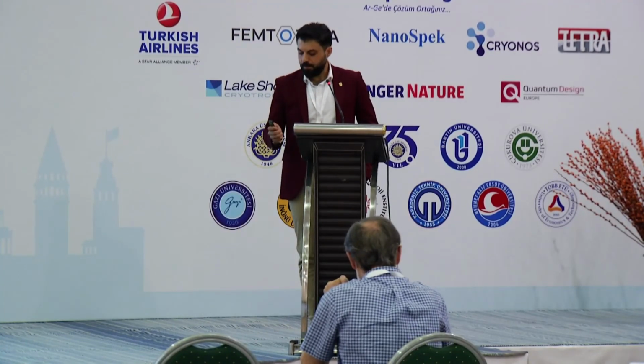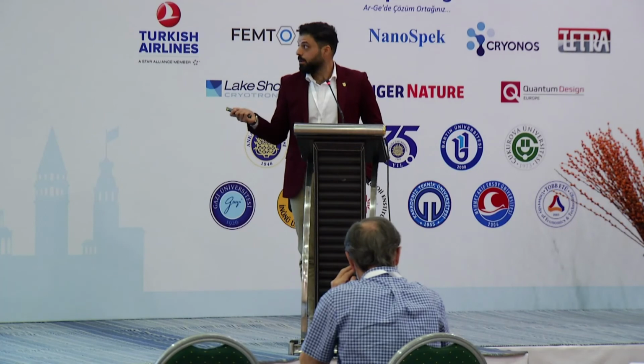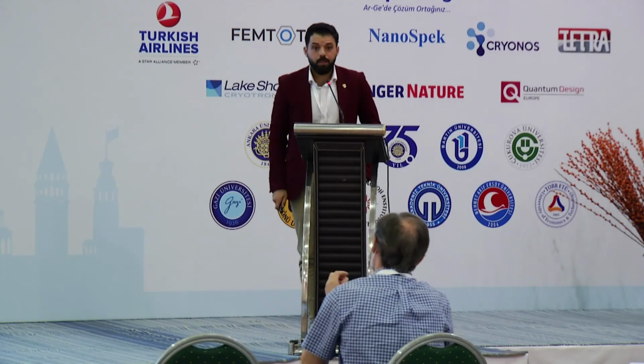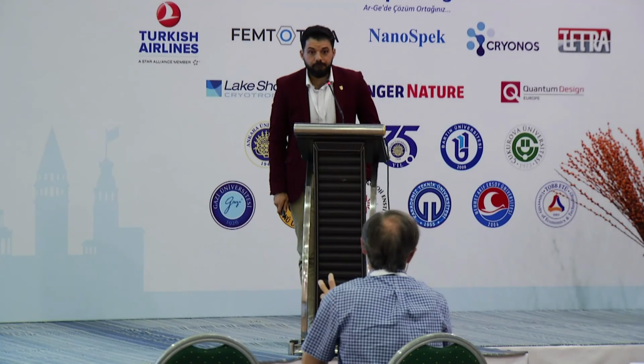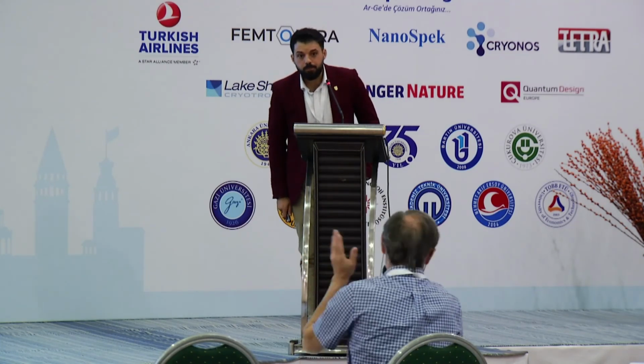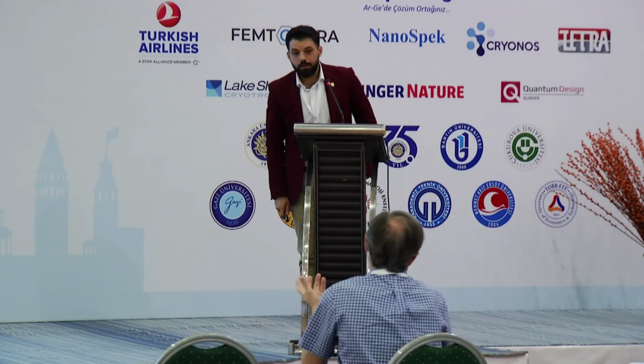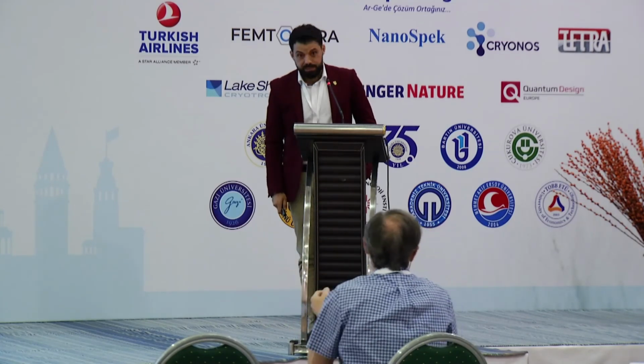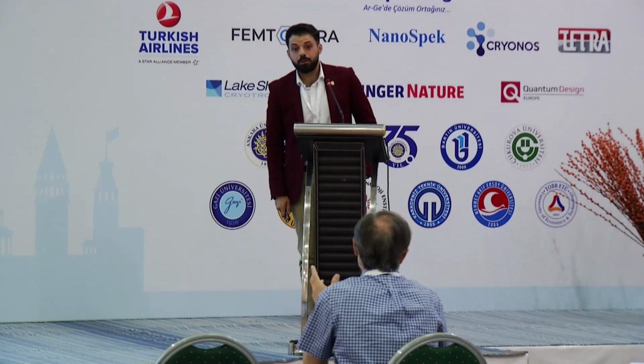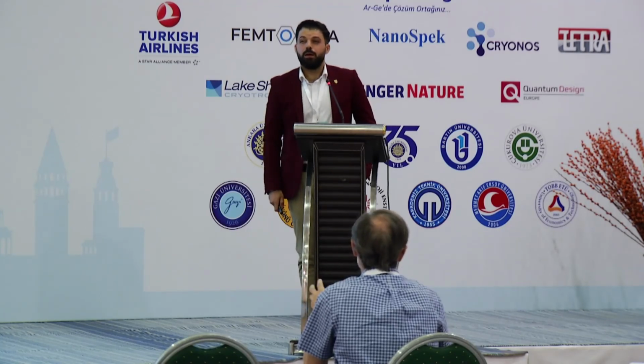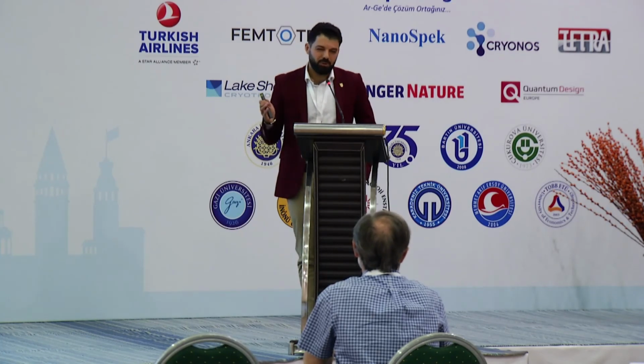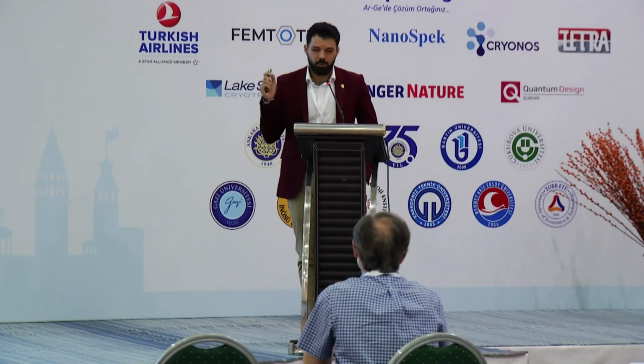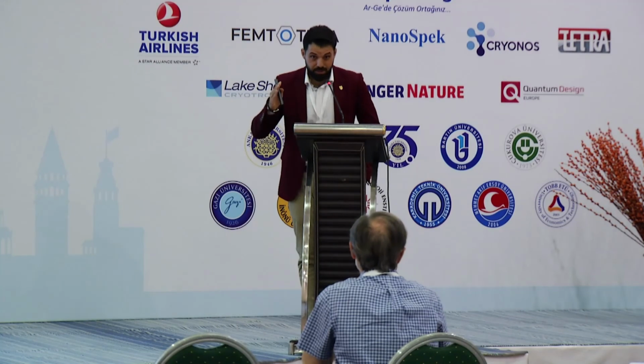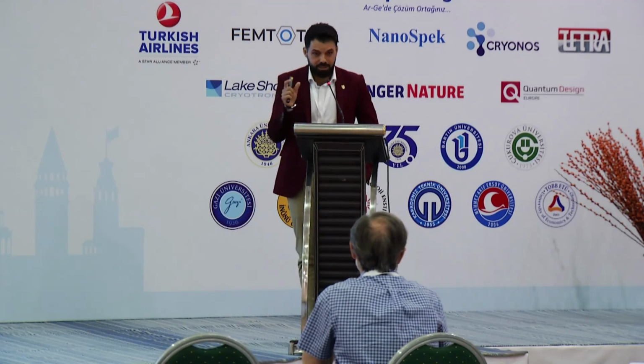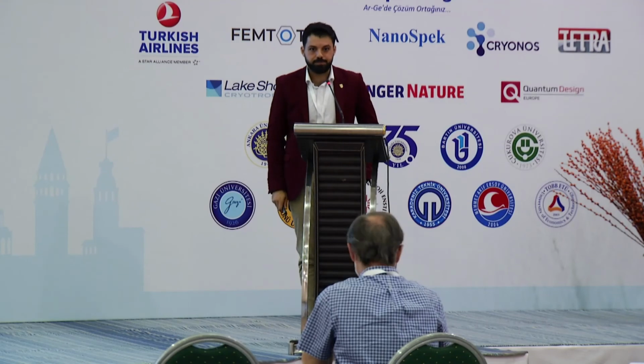Yes. The other one is, when you say you reach an optimum spectral range, I guess for photocatalytic activity, coming towards the visible, right? And you would like the photocatalyst to work with sunlight if possible. Yes, sure. It looked like it had a maximum in the blue part of the spectrum. Is that correct? Yes, the maximum was mostly a near band gap edge emission, which is in the violet region. But as you see from the chromaticity diagram, there was a shift in the color coordinates, which means that we can harvest a larger amount of the visible spectrum.